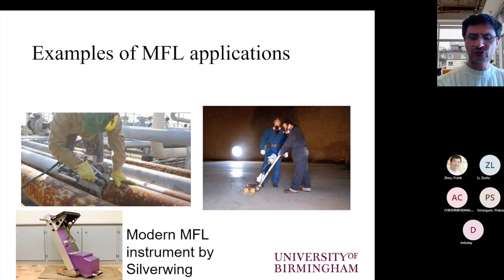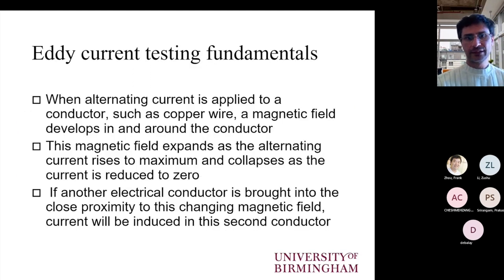And of course, we can use MFL for inspection in railways. So it's one of the classic approaches for railhead inspection for rolling contact fatigue defects, as well as defects that lie in the railhead or in the top part of the railhead, because as we go deeper, the magnetic flux does not penetrate, and of course, that doesn't allow us to inspect other parts of the rail or the bottom part of the railhead.